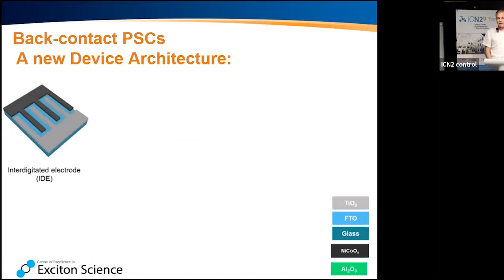Now, how do I make an interdigitated electrode? The easiest way is to have two sets of electrodes like this. This one here is collecting my electrons. This one here is collecting my holes, and they both sit underneath the perovskite. A disadvantage compared to silicon is that silicon has a charge carrier diffusion length of millimeters. In a perovskite, if we're very lucky, we have micrometers. So we need to make sure that whatever structure we create underneath our perovskite also has feature sizes in that micron, even submicron, ideally, space.